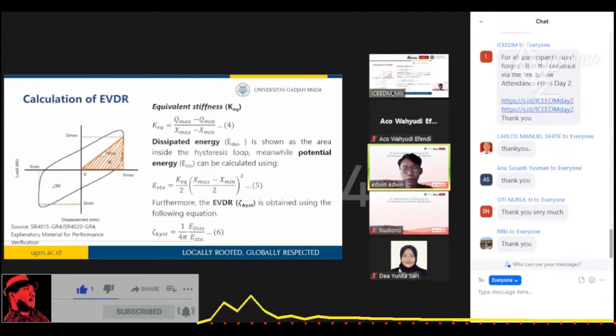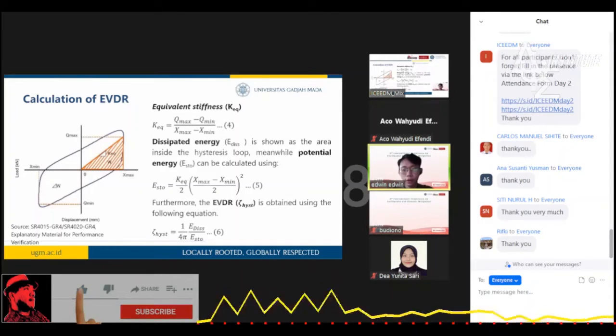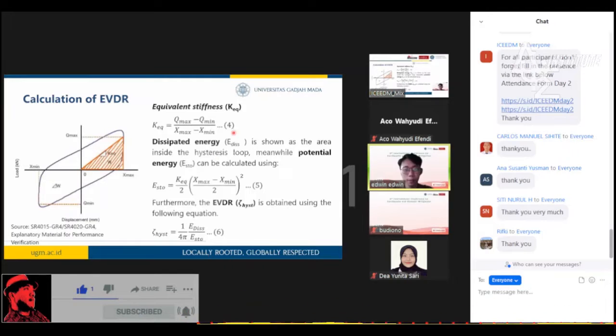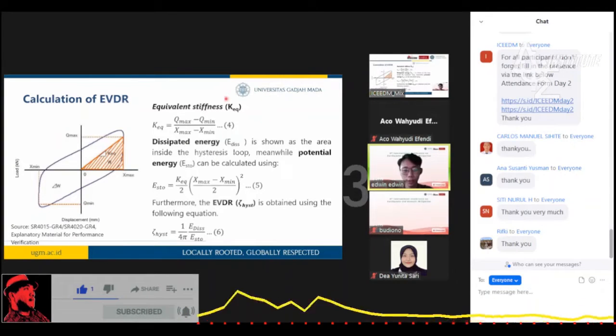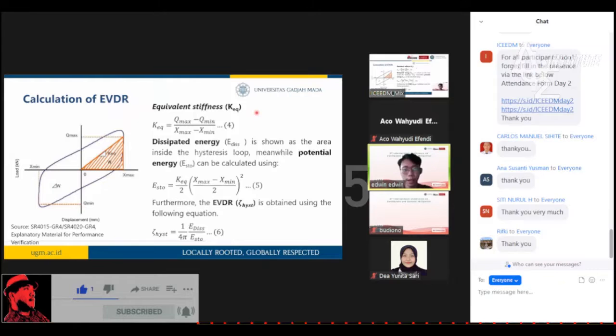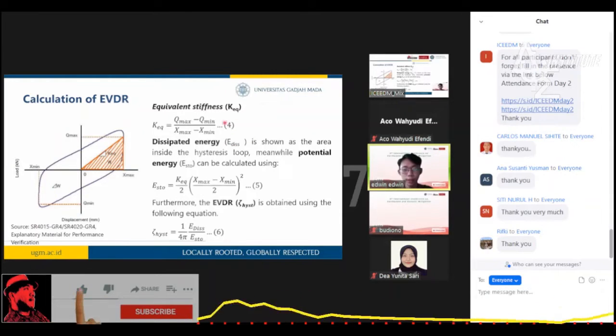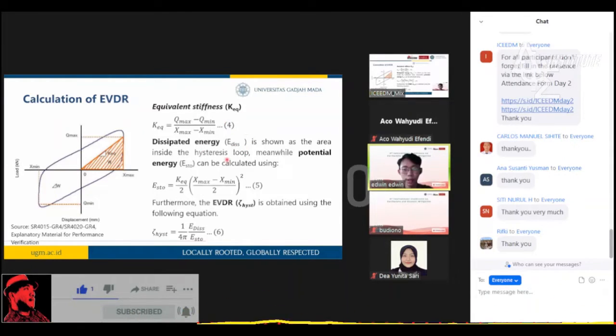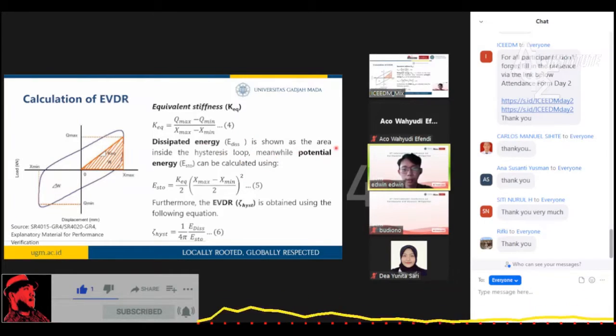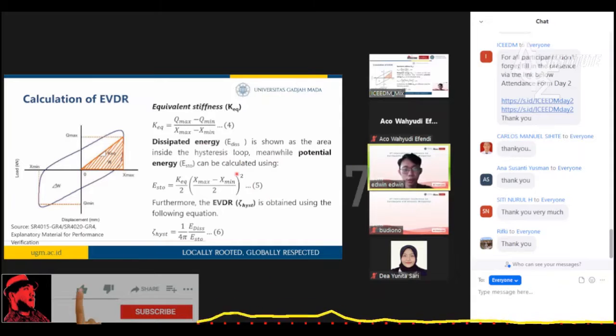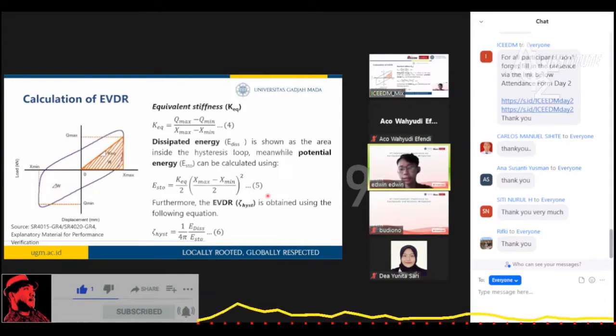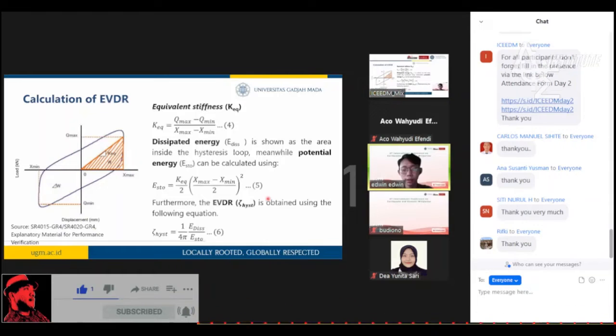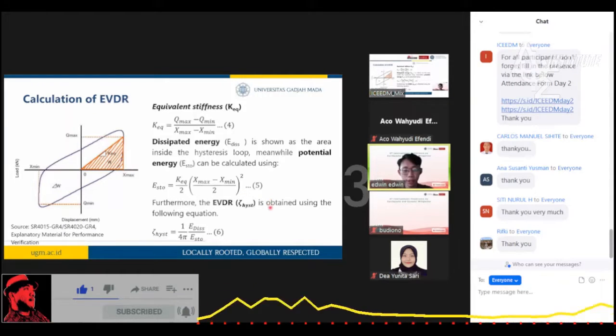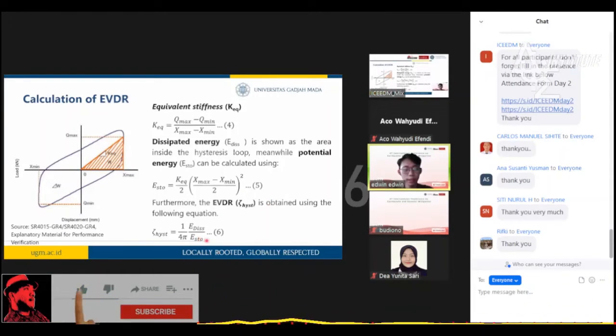And the method used to calculate damping ratio in this research was equivalent viscous damping ratio. The first step was to calculate equivalent stiffness using equation number 4. And then we can calculate the dissipated energy that was the area inside the hysteresis loop. And after that, we can calculate potential energy using equation number 5. And lastly, we can calculate the equivalent viscous damping ratio using equation number 6.